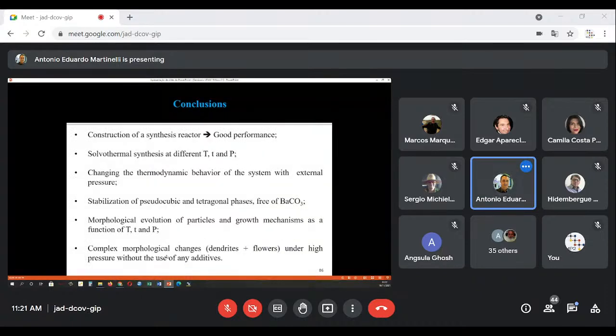So to conclude, this work showed the construction of a synthesis reactor that allowed the application of external pressure. The reactor performed very, very nicely and still does these days. So we investigated solvothermal synthesis processing at different temperatures, times, and pressures applied to barium titanate. We could see the change in the thermodynamic behavior of the system with external pressure resulting in different morphologies, but the purity of the phase was maintained.